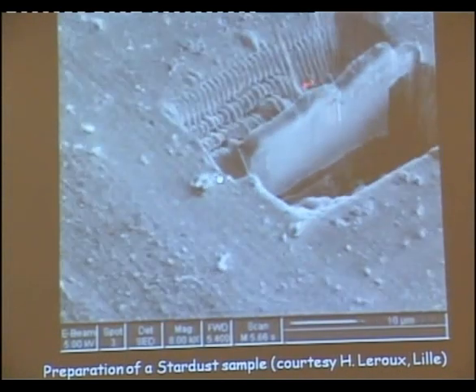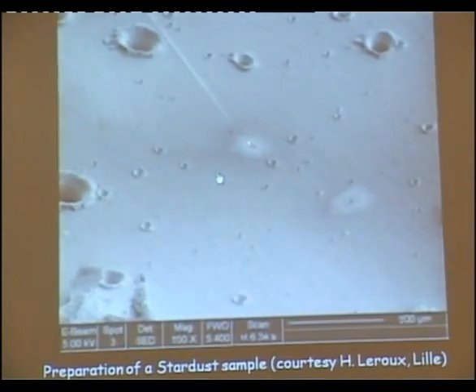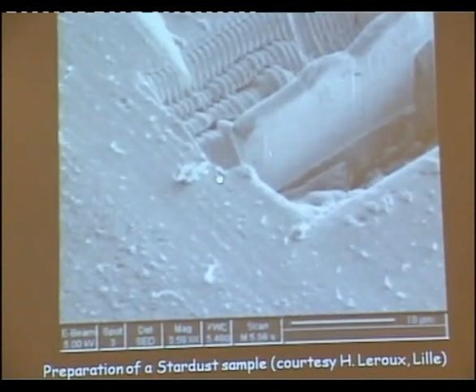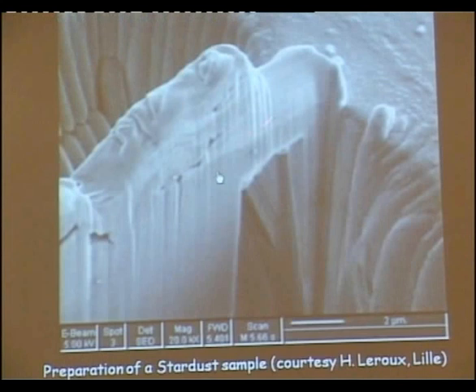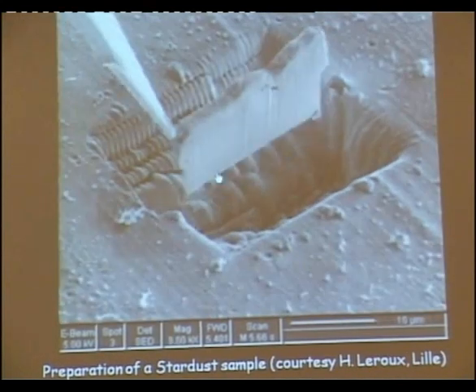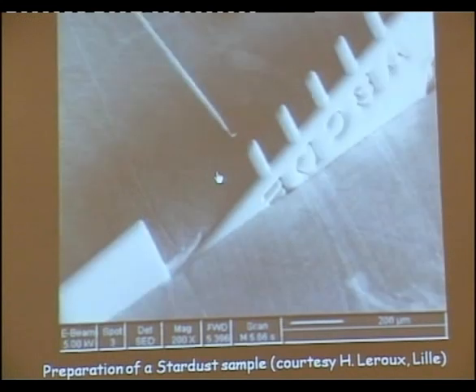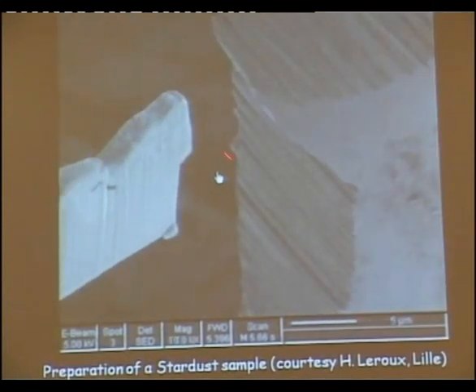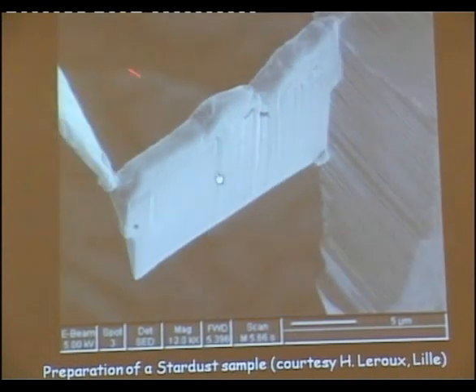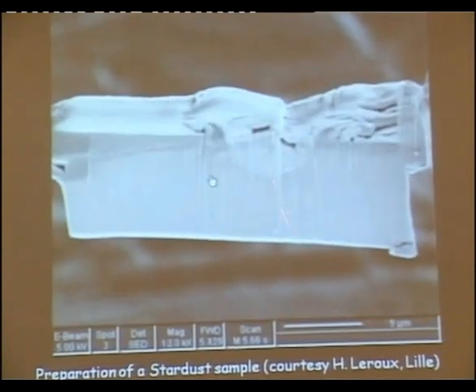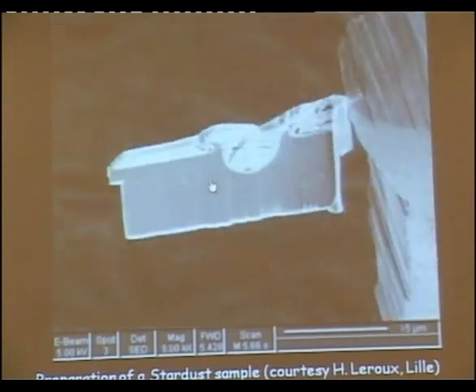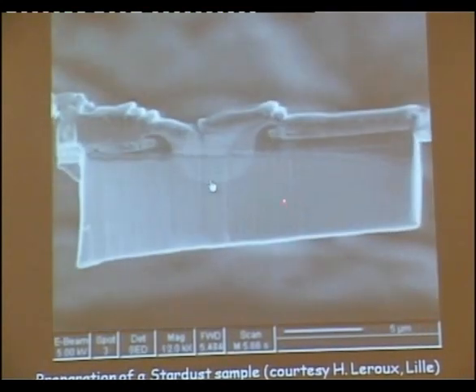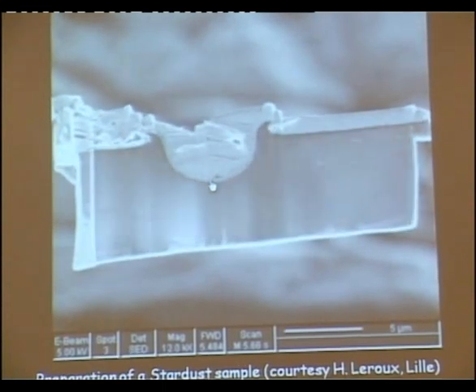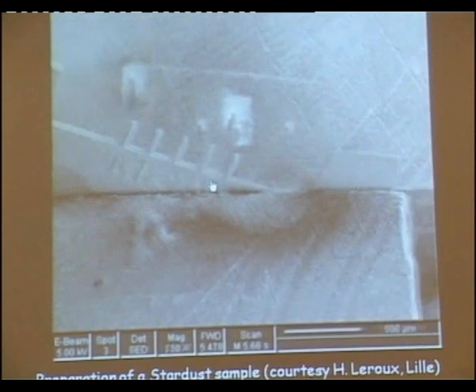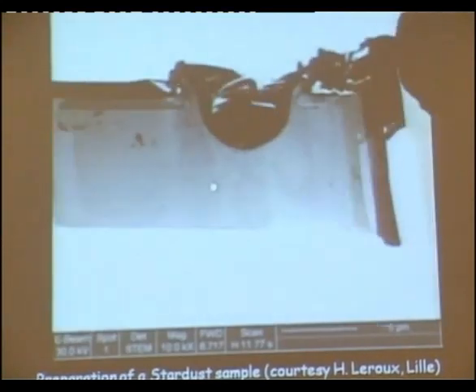You see, it's now cut, and now they approach the needle to the sample and glue the needle to the cross section with platinum, and then they cut here. So now they can remove the cross section. They bring it to the sample holder that is used for TEM. They glue the sample with platinum, cut here, and now they thin down the sample. Now we have a cross section that is 100 nanometers thin, and you can put it in the TEM. So we can use this sample for transmission microscopy, and that's the TEM view of the sample, where you can look down to the nanometer scale.